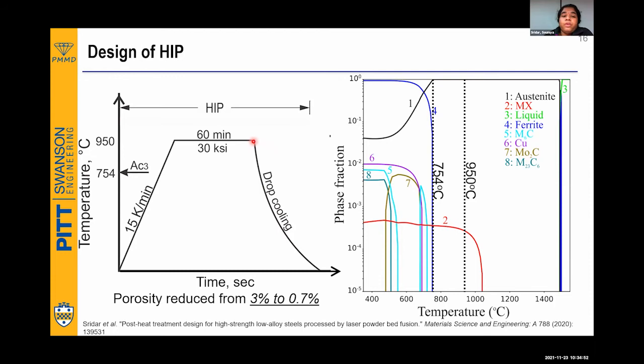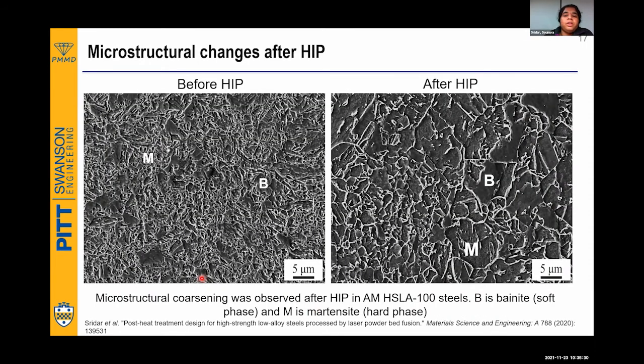We found that this profile was expected to spoil the microstructure less. I'll show you in the next slide how it spoils the microstructure, because it is really a spoiled microstructure that we got after that. But the good fact we should be happy about is that the porosity reduced from 3% to 0.7%, which is a very good number. Whatever we wanted has been achieved. Yes, we reduced the porosity thanks to HIP, but my microstructure is gone. It has terribly coarsened the microstructure.